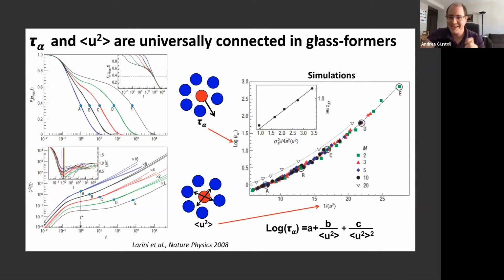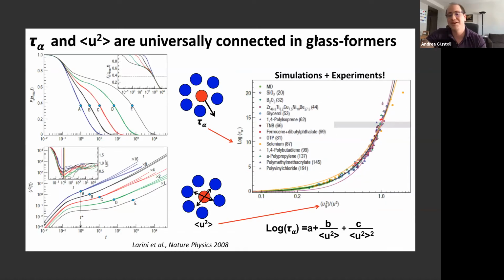The cool part is that, okay, this is simulation, but then they tested it in the same paper for experimental data. And this plot shows that this scaling works over 20 orders of magnitude for simulation and experiments. And you can see here you have silica, metallic glasses, glycerol, polymeric materials. It's a huge variety of systems that all behave in the same way.